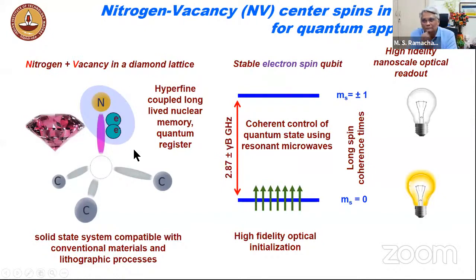And as you can see the arrow, this is a center. So the first thing to understand is that pure materials are not always the best. We need to have defective materials. And as Professor Rao had also talked about showing defects in one of the TEM images, similarly here you can see that we are doing doping, much like silicon is doped with phosphorus or boron to create PN type of silicon. Here we have one nitrogen, but this defect also includes a vacancy. So when a nitrogen and a vacancy, which basically means an absence of carbon, come together, this is what makes diamond pink if you create enough of these vacancies. But typically we deal with much lesser, in the order of parts per billion or parts per million at most.